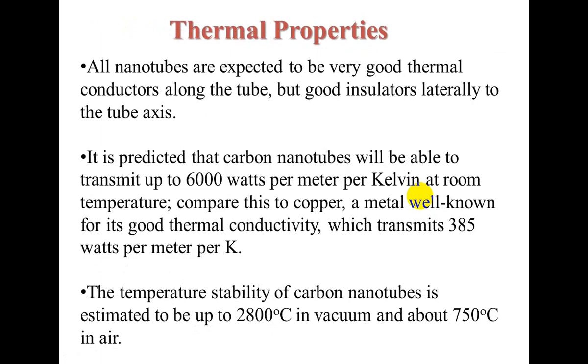Thermal properties — all nanotubes are expected to be very good thermal conductors along the tube but good insulators lateral to the tube axis. It is predicted that carbon nanotubes will be able to transmit up to 6000 watts per meter per Kelvin at room temperature, compared to copper which transmits only 385 watts per meter per Kelvin. The temperature stability of carbon nanotubes is estimated to be up to 2800°C in vacuum and above 750°C in air.